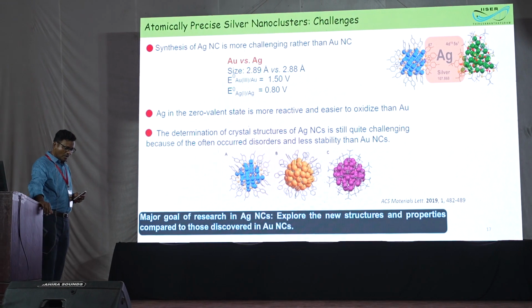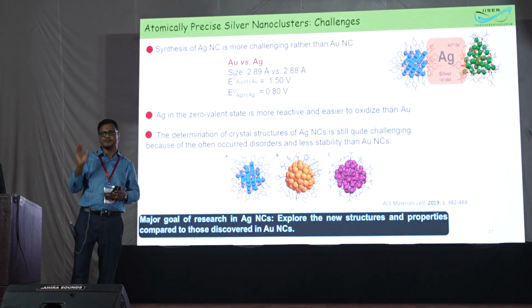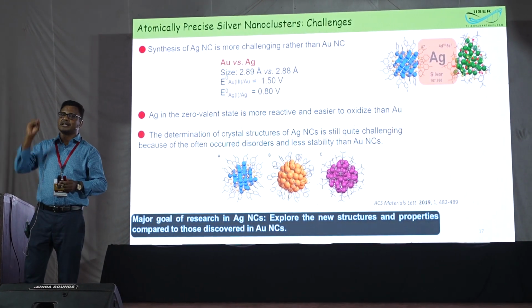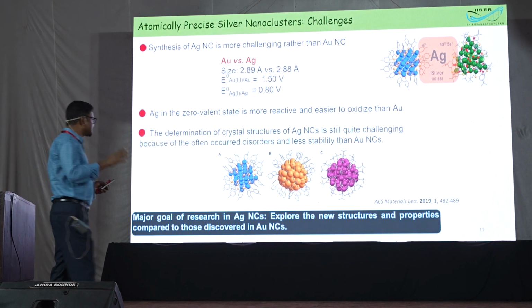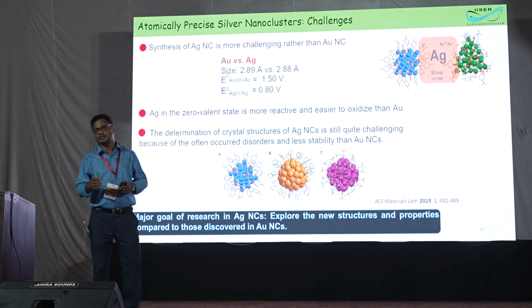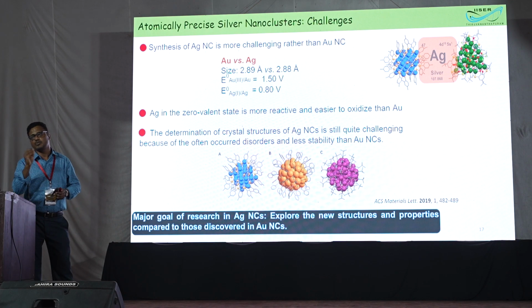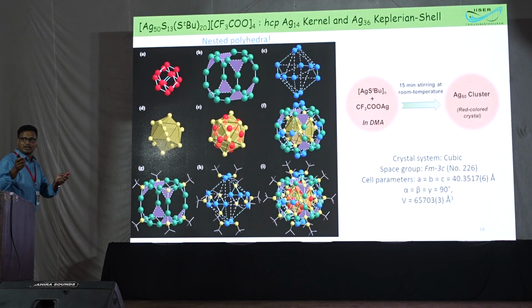First of all, when you crystallize silver, all reactions have to be done in the dark. Crystallization you may get, but the crystal structure solution is challenging because of a large absorption problem and poor quality data. With that, we have some contribution on this.